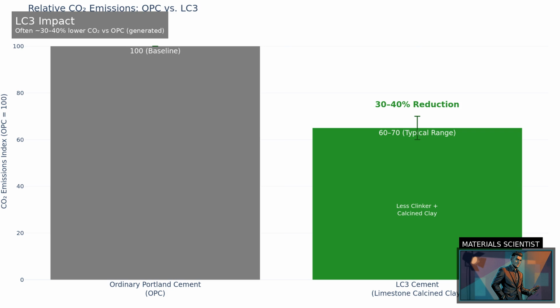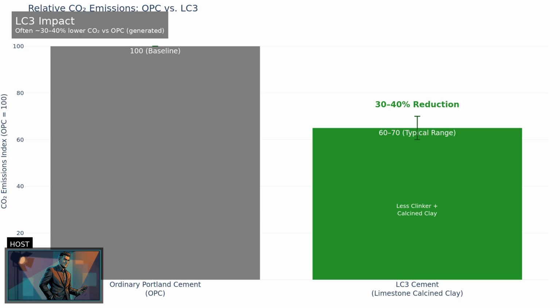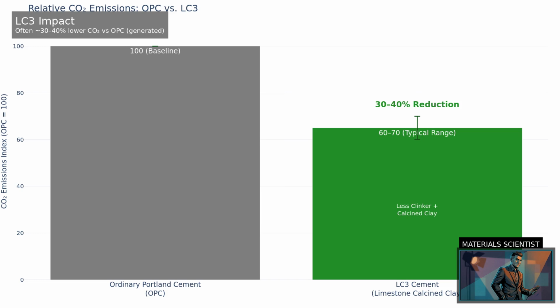And it's not just lab work anymore. In 2025, Noida International Airport in India announced it was using LC3 at large scale in its construction. Okay, 40% is great, but that still leaves 60% of the emissions. We still have to burn fuel to heat the kiln, right? Exactly. That's where the heavy artillery comes in. Carbon capture and storage, or CCS. If we can't stop the chemistry from releasing CO2, we capture it before it escapes the stack.